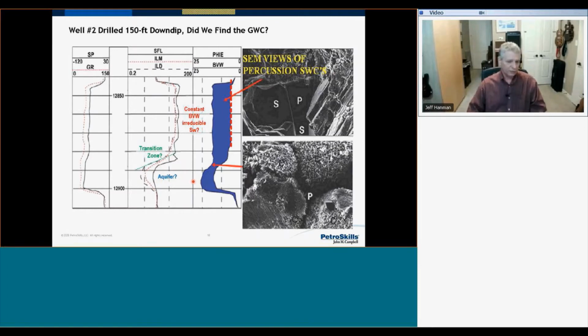We did get a bit extra information in this particular well. We have SEM images from 2 percussion sidewall cores. Just a word about percussion sidewall cores. Many of you may not have very much experience with those, but when I first started, they were common in just about every well because they were fairly inexpensive, and it was a chance to get a direct sample of the reservoir rock. In this particular case, the SEM of the percussion sidewall taken towards the top of the reservoir has a lot of cements, a lot of overgrowth. You can see these faces as we grow the cements on the grains, whereas this sample, from where we see the porosity increasing, has a clay coating on the grains, and you see the pore reasonably well preserved.